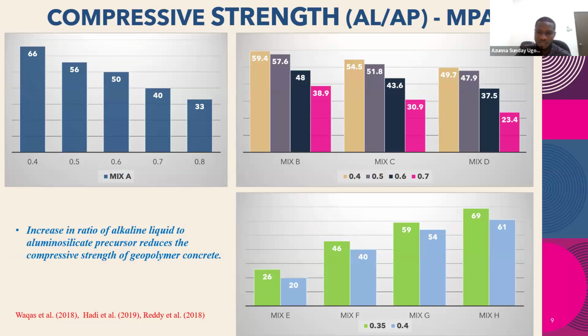Then the next thing that affects the compressive strength is the alkaline liquid to binder ratio. Like I said, it's like the water cement ratio in your normal cement. So if you use a higher alkaline liquid to binder ratio, you're likely to get a lower strength, because what it means is your binder is less, you have a higher amount of alkaline solution. So the implication of that is geopolymerization will not take place very well. It will not be effective. You have a lot of water. Your mix may have a high workability, but your strength will be very low.